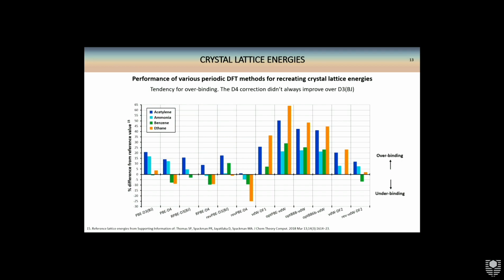Next up, we looked at crystal lattice energies. This is a similar plot to before in terms of it being a percentage difference between the calculated and the reference values for crystal lattice energies. But for this, we were realistically only able to get four systems to have the crystal lattice energies, because it gets a little complicated when you start thinking about co-crystals. The positive values on this mean that the functional is overbinding a system and the molecules are interacting too strongly, and the negative values mean they're underbinding and the crystals aren't being held together as strongly as they should be.